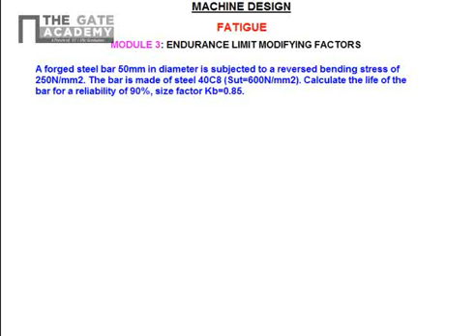A forged steel bar 50 mm in diameter is subjected to a reversed bending stress of 250 Newton per mm square. The bar is made of steel 40C8, which is the grade of the material, with SUT of 600 Newton per mm square. Calculate the life of the bar for reliability of 90% and take size factor as 0.85. Now, how do we solve this problem? First we find the endurance limit of a rotating beam specimen. We know that Se dash is given as 0.5 times SUT, that is 0.5 into 600, which is 300 Newton per mm square.